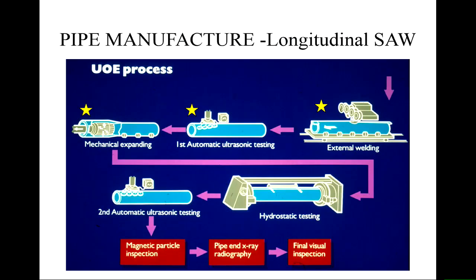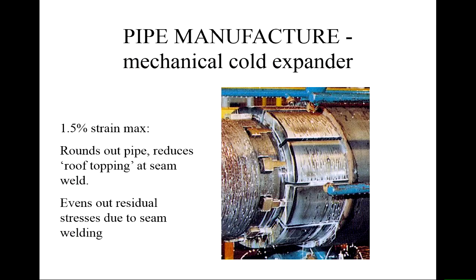Okay, what about expansion? Well, you've got this big internal clamp, and it's a mechanical process and it's cold. And what we're doing is we're just expanding that pipe. So we have a cam-driven system which has the segments, these outer segments that you can see here, which are just forced apart. And typically we expand to around 1 to 1.5% strain. So we're increasing the circumference of the pipe by 1.5%. And that will even out any residual stresses due to seam welding, and it will reduce what we call roof topping at the seam weld.